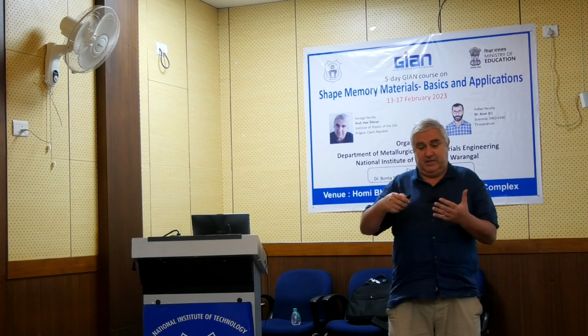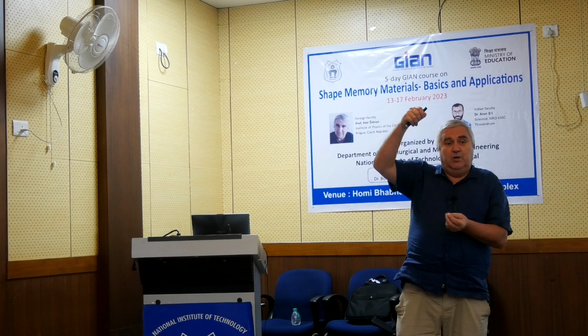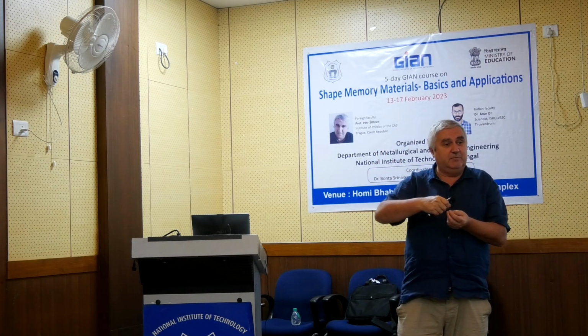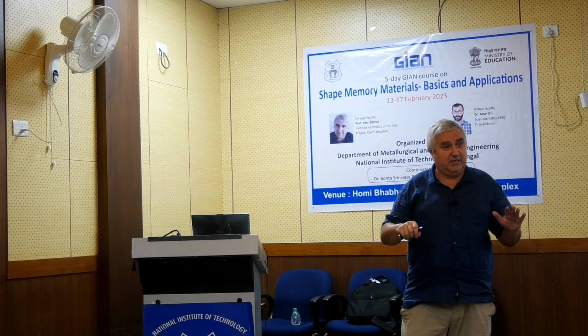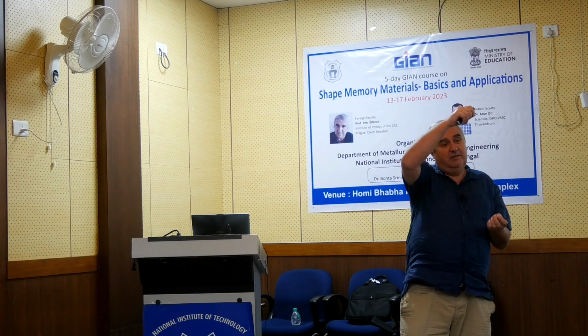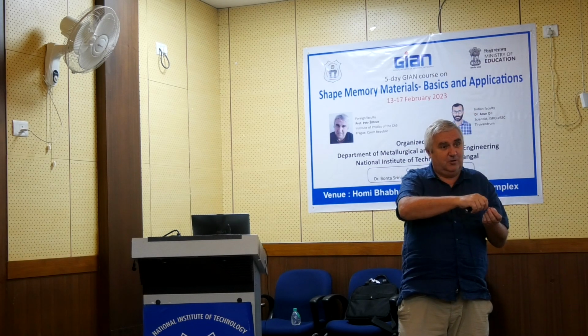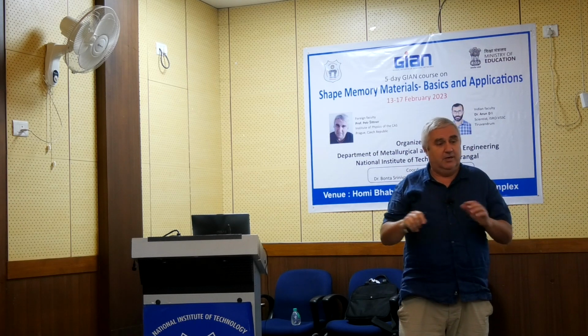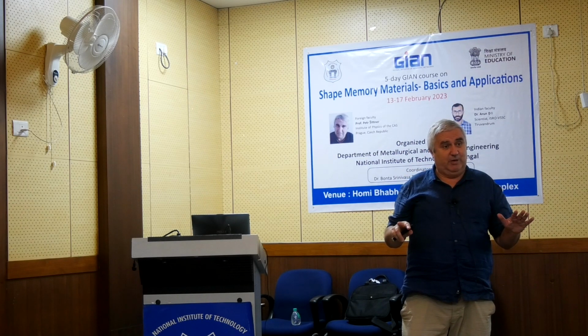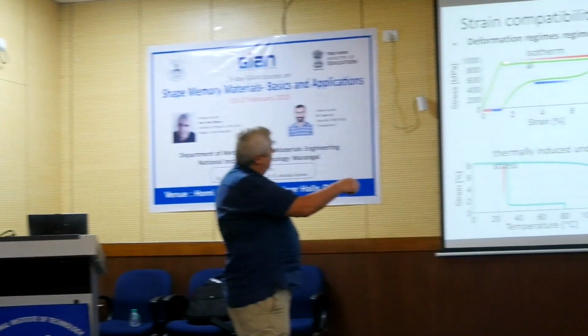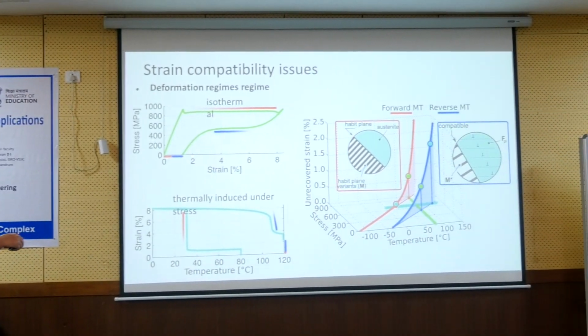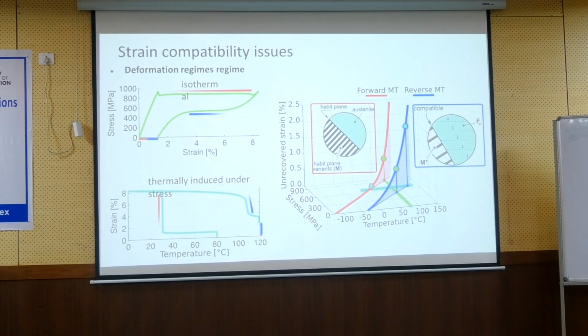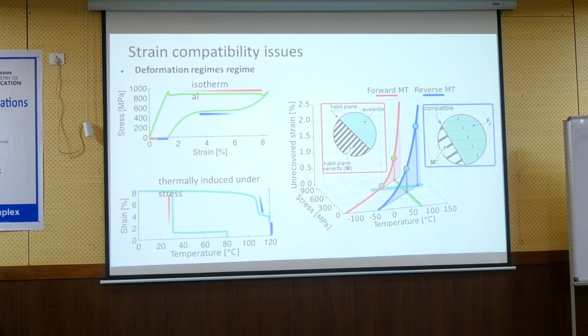In other words, if I have the austenite and I load it to 1 gigapascal 20 times, there will be no plasticity. At high temperatures, no plasticity. If I have the martensite, I load it, unload, cool, and you do shape memory effect. So I load it to 1 gigapascal, unload and heat, no plastic deformation. But if I perform a cycle when it transforms under 900 megapascal, very big unrecovered strains. So this plastic deformation occurs when the transformation proceeds. And that's a problem, because you cannot get rid of that, because you want to utilize the transformation and the plasticity comes along.